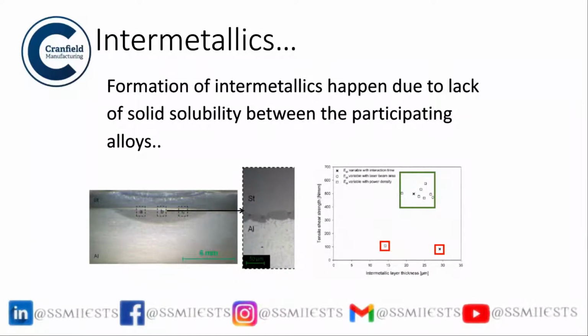So how do we join this? We put a laser on top of this. As you can see, here is a small melt pool of steel, but we try to control the heat in a manner that the heat will conduct through the steel to the aluminium, and this aluminium is now molten, and at the interface the aluminium wets the steel. This way, you can prevent an intermixing of steel and aluminium, and that will prevent formation of a tremendous amount of intermetallic compound, which will make the joint practically unviable.